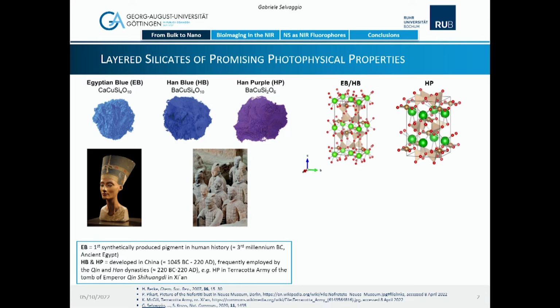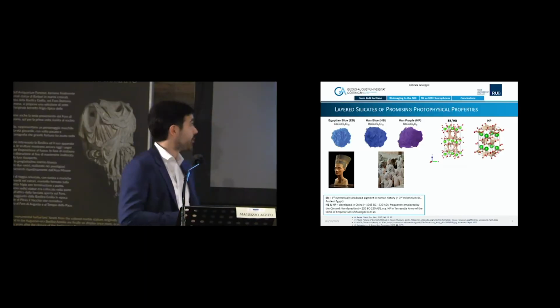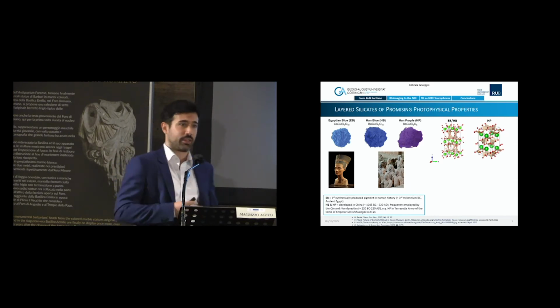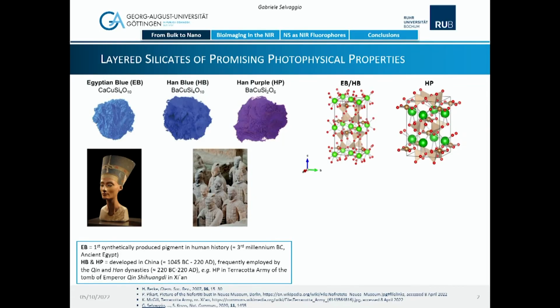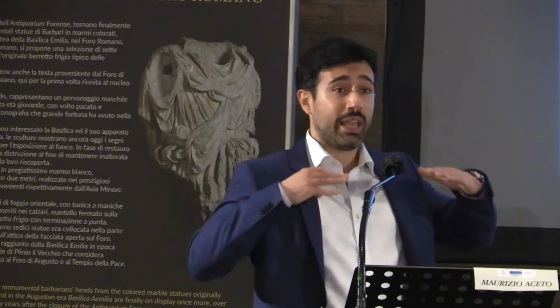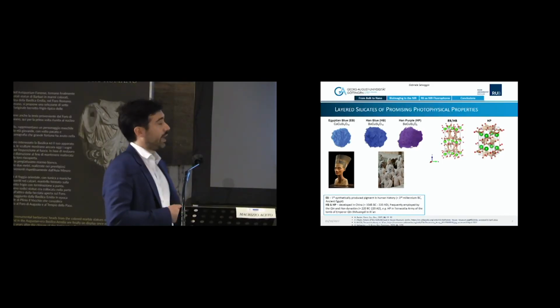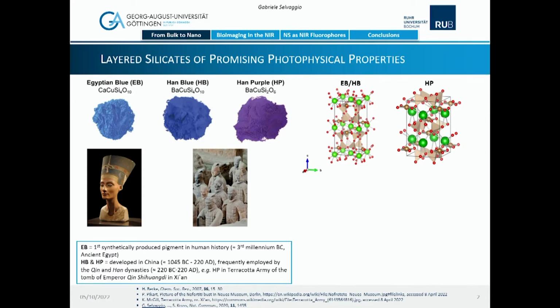Crystal structure that was very nicely described by Professor Chiari earlier. In the case of Egyptian blue, but also Han blue and Han purple, we deal with layered silicates. Therefore, silicates which are displaying layers, so silicate tetrahedra displayed in layers, and these layers are held together quite weakly by either calcium or barium ions. And in this way, these materials are prone to be exfoliated into 2D materials.